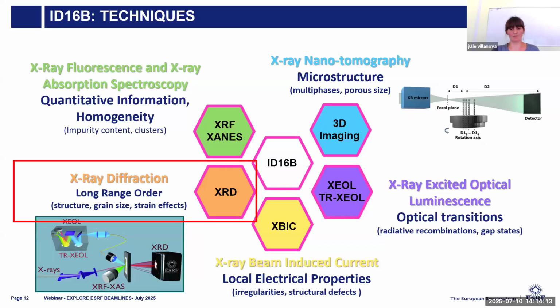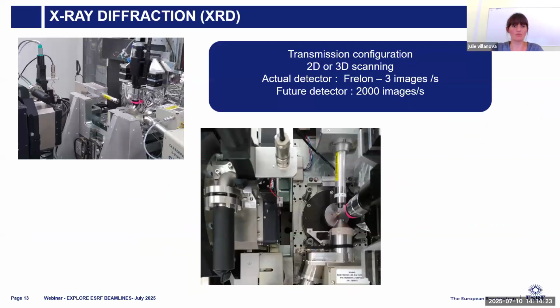So coupled with this fluorescence, we can adapt some diffraction detection, so we can also perform simultaneous measurement. What is important to understand about this configuration at the beamline is the picture of the setup: we still have the X-ray coming from the right. You recognize our two fluorescence detectors, and here we have the diffraction camera. We work in transmission mode, and we can adjust the position of the camera to adjust the angle we are looking at, but we do not have a goniometer.